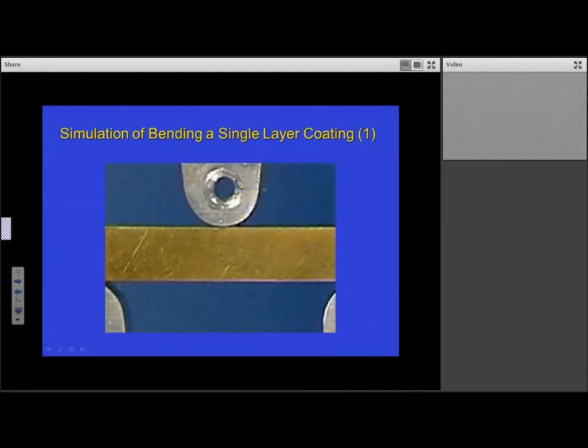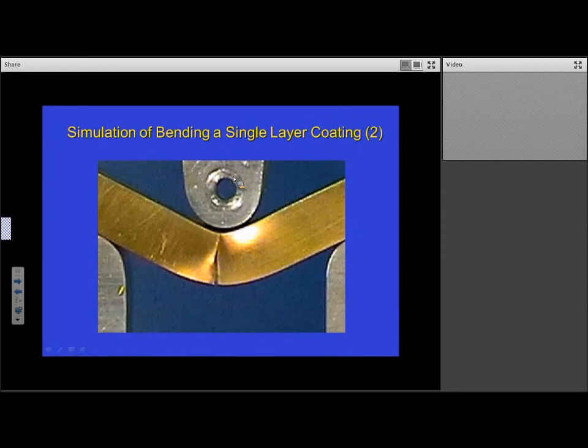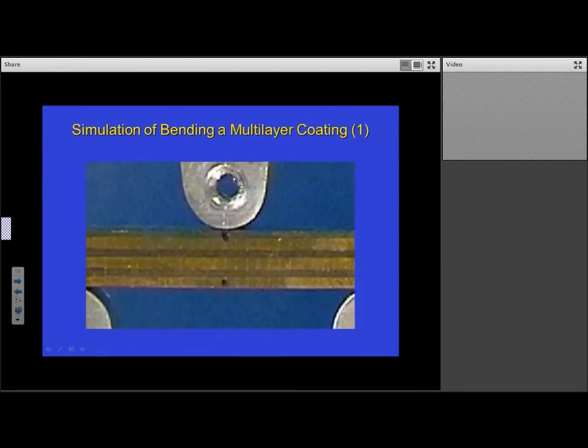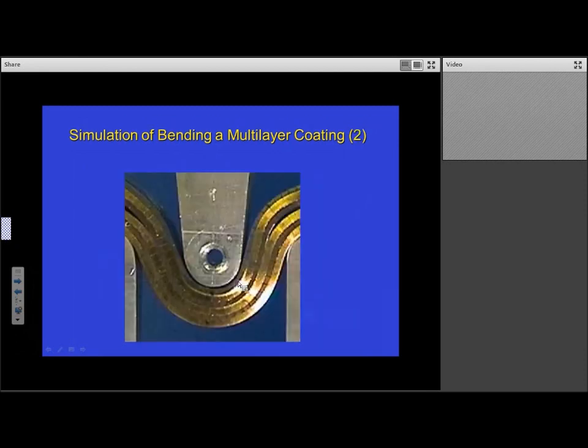So if you consider this as a thick coating, and you load it, and the substrate deforms, the coating could crack. If, however, you have a thick coating which has layers of hard, soft, or high modulus, low modulus is another way to think of it, and you load it, then it won't crack because the hard layers are thinner, so they don't see such a high bending stress, and they're allowed to deform because the shear takes place in the soft, low modulus layers.